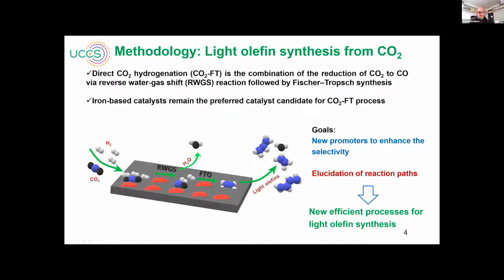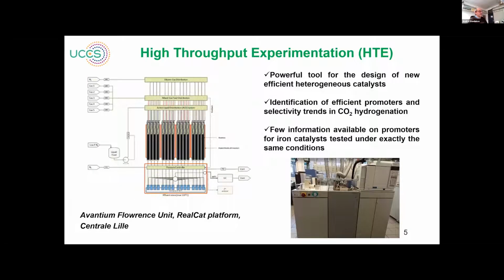So, of course, the catalyst has to be more complex than the catalyst we use for conventional Fischer-Tropsch synthesis, because it's a combination of several reactions. It can contain different promoters, different components. So the goal of our work was that we started with an iron catalyst, and we were searching for new promoters to enhance the selectivity. At the same time, we conducted a large number of experiments, which I will show in my presentation, and we try to see the reaction path which occurs during CO2 hydrogenation. These two types of information will lead us to the design of a new efficient process for light olefin synthesis.